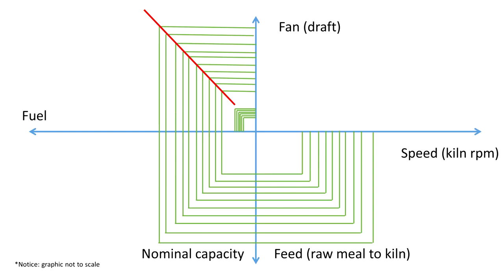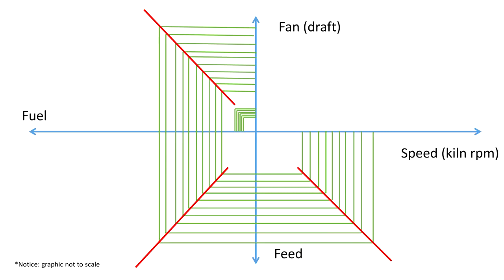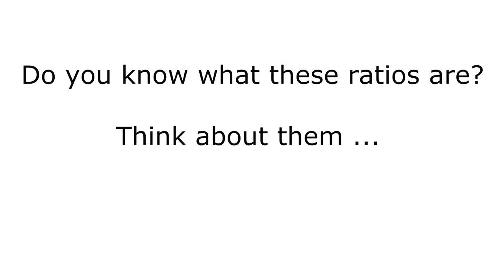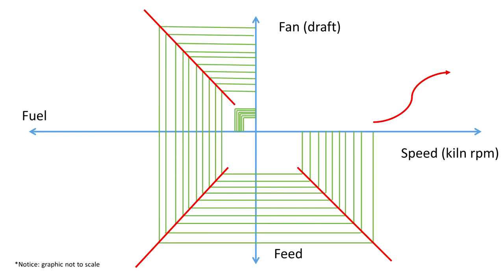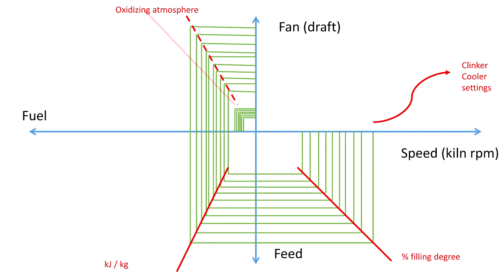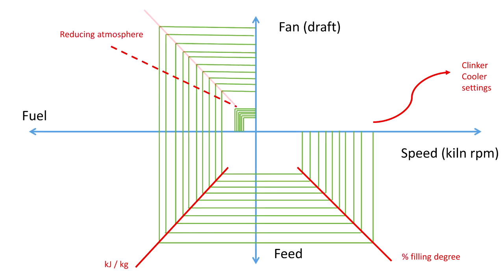If you notice, there's a ratio between these parameters, even with the kiln speed. Do you know what these ratios are? Think about them for a moment. The first one is simply the O2 content, then the specific thermal consumption, the kiln filling degree, and the settings on our clinker cooler. Changing the slope of these ratios will affect the behavior of the system as shown.